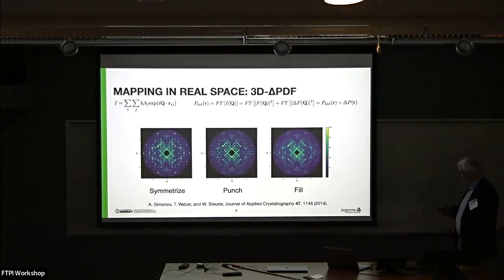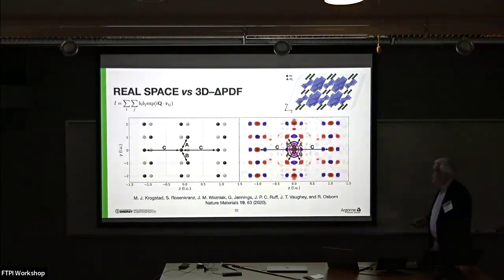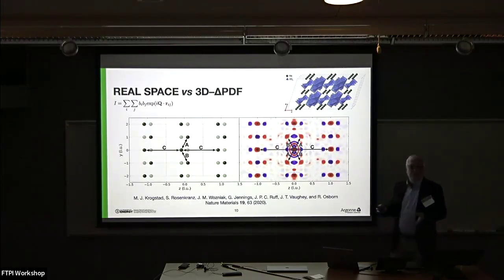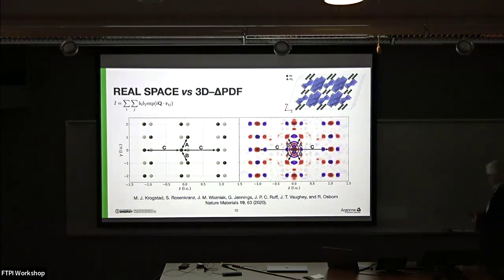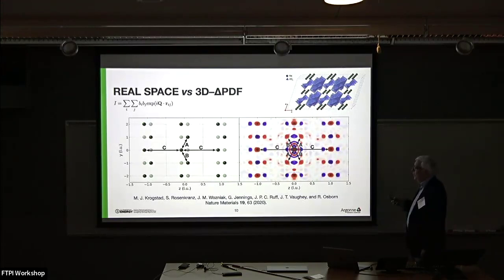And we now implement that on a routine basis. And to understand what you can learn from that, if you transform data across, you can get these complicated distributions of diffuse scattering intensity over Q space, which just don't mean anything if you look at them. You might see a few features that you think you understand. They get transformed into discrete sets of interatomic vector probabilities that correspond to interatomic vectors in the crystal structure. And indeed, you filtered out all of the average vectors, so you're left with only those that differ from the average. And in this case, as a simple example, this is sodium intercalated V2O5. The only disorder is then in this partially occupied ladder, set of penetrating ladders. And so the only features we see come from the ladders.